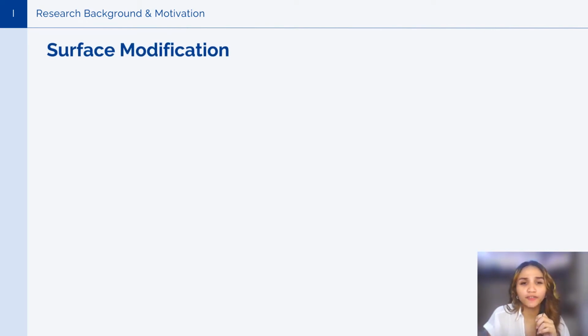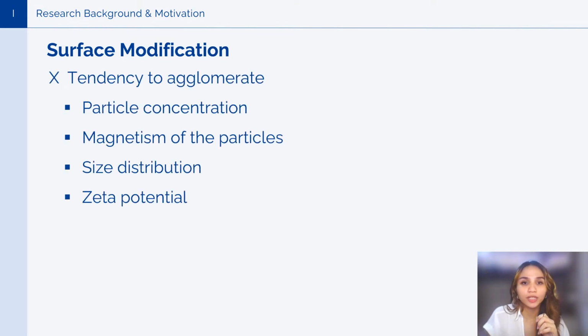In spite of their effectiveness in the removal of contaminants, nano-zero-valent iron still has some weaknesses. Aggregation of bare nZVI particles decreases its surface area, which decreases the mobility and reactivity, thereby limiting the radius of its influence. Several conditions causing the nZVI particles to agglomerate include the particle concentration, the magnetism of the particle, the size distribution, and zeta potential.